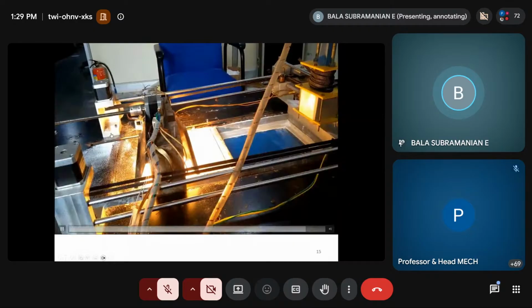Okay, so the temperature ranges. The ceramic infrared heater can go up to maybe 300 degrees C max. Polymer powders have a melting point of about 200 or 250 degrees C, and we need almost 80 to 90% of the melting point. So we may need around 180 to 200 degrees C as the sintering temperature. So we are able to manage it with the ceramic infrared heater for materials with that melting point.